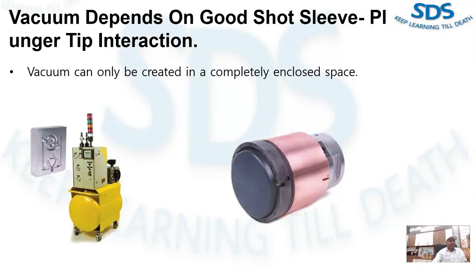If alloy then collects on the plunger tip, rapid deterioration of the vacuum seal will result as the tip becomes galled and the sleeve becomes soldered. If close control of this tip sleeve gap is lost, a good vacuum can be easily destroyed in less than a thousand shots.